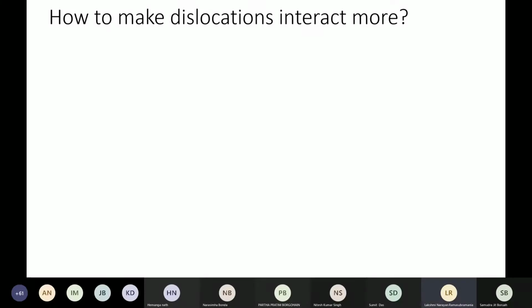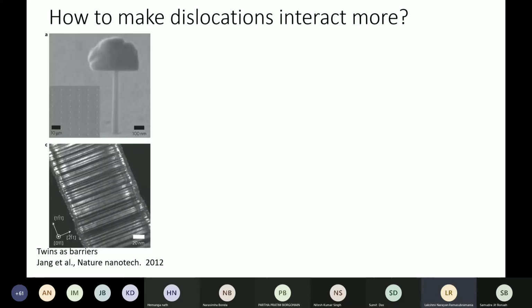So our idea is we need to make sure that ductility improves. And for that, we see that dislocations should not be allowed to escape the crystal. If they are allowed to escape the crystal, immediately deformation will concentrate at that line in which the dislocation has exited the crystal, and it will keep increasing the stress over it. So how do we do that? We are going to build a specimen which has got barriers in it. We are going to make materials which have barriers in them.